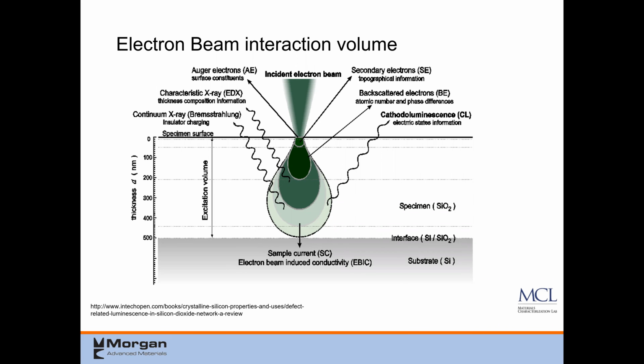So what happens when the electron beam hits the surface of a sample is that a bunch of different things come off the surface. You get backscattered electrons and secondary electrons, and that's how we do our imaging. You're also emitting cathodoluminescence and some Auger electrons, but the ones that we care about are the characteristic X-rays, and they come from a little ways down in the sample. So this is more of a bulk technique. It's not a surface technique.